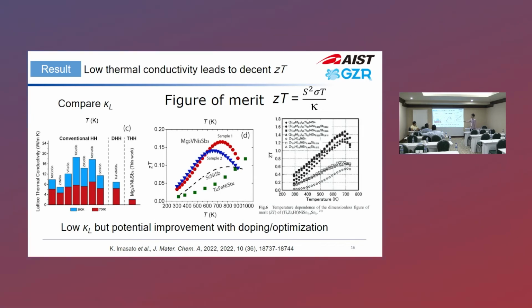Compared to other well-known conventional Half-Heuslers, they have like 10 to 20 at room temperature and somewhere around 8 at the higher temperature. But this is our result for the triple Half-Heusler, so it looks like a very small thermal conductivity. And ZT is still less than 0.2, so not very good, because the highest one is like 2 or 2.5.